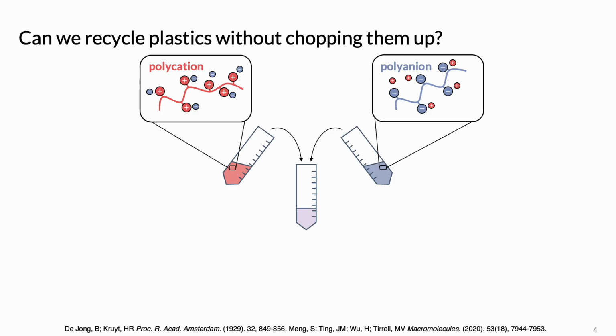Part of my goal was to find a way to create a plastic that was actually recyclable, meaning that the recycling process didn't chop up the long-chain molecules. And there is a way that we know how to do this, and it comes from what we know about charged polymers, or polyelectrolytes. These charged polymers have either positive or negative charges spaced out along the chain. If it's a positive charge, it's called a polycation, and if it's a negative charge, it's called a polyanion. And there are many different charges that can go on a polycation or polyanion.